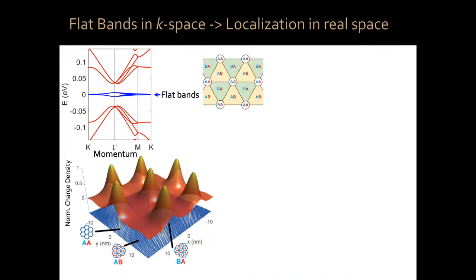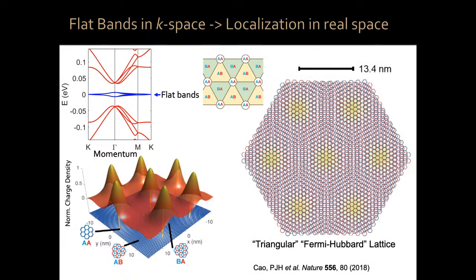In a slightly more realistic schematic, this is what magic angle twisted bilayer graphene looks like. You have these regions where the yellow shading is. Those are the AA regions where the electrons like to sit. Those regions are separated by about 13 nanometers. So this is going to form the equivalent of a triangular Fermi-Hubbard lattice for my cold atoms.